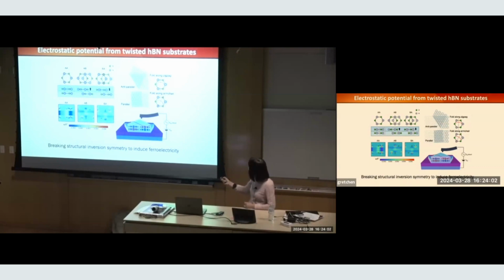And interestingly, my student started doing this by folding the layers. You know, tear and stack is very painful, and you don't make many. My students started just blowing a nitrogen gun at these layers, and they will fold. They either fold along armchair or they fold along zigzag directions, and half of the samples would have ferroelectricity in them. So 50% isn't too bad. So we live with that.